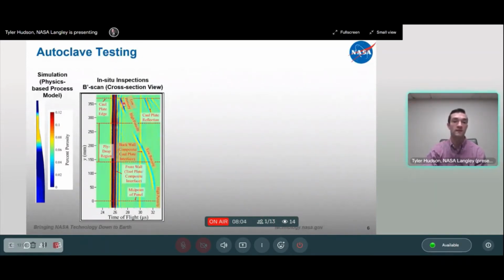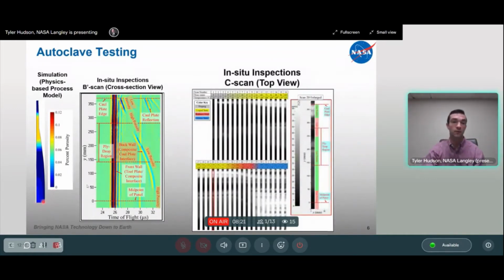And what you notice is that on this back surface of the composite, you have two areas of high porosity, denoted here by a low amplitude, and in the center, denoted by a low amplitude. And that corresponds exactly to where the porosity is predicted from the process model. This is a through thickness view.